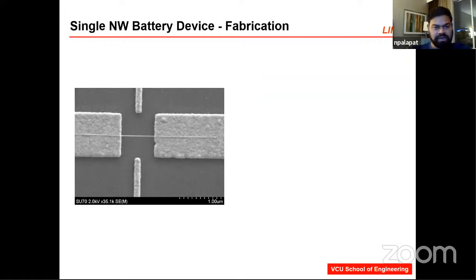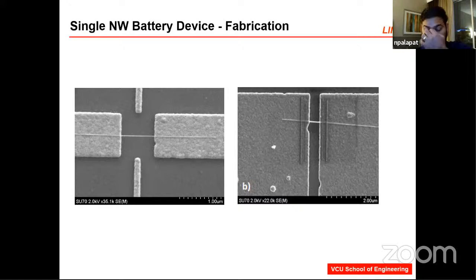This is a scanning electron microscope image of that small location that we saw in the optical image. As you see, the nanowire is perfectly centered at the center of the electrode, and then we perform additional tests to characterize whatever we need. So this is another nanowire that is deposited.